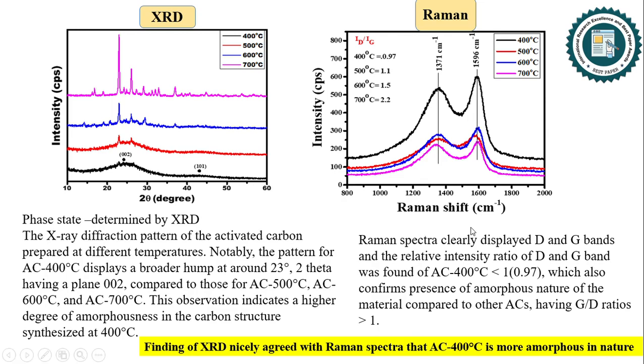The Raman spectra clearly displayed D and G bands, and the relative intensity ratio of G and D band was found to be less than 1, that is just 0.97, which also confirms the amorphous nature of the material compared to other activated carbons having a G to D ratio greater than 1.